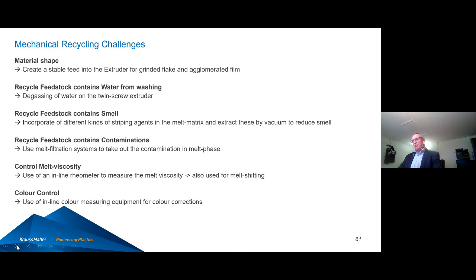Melt viscosity, very important. What you do up front is you mix as much as possible your polymer streams, like already has been shown before by Jan. When you look over the time, what is the viscosity of the different streams? As long as you gather enough and mix them enough, the stream will be pretty in line over the time. You have to do mixing, and what we do on our lines is we install an inline rheometer to measure this viscosity. And when you do, for instance, polypropylene melt shifting, the feed of peroxide to do that, we can already measure the melt flow index over a continuous rheometer, and then correct this by the peroxide feed at the beginning of the extruder. So also these kinds of things with quality are working, and we have it available.